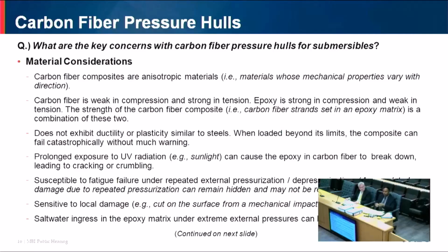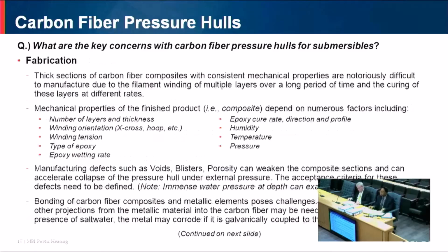Okay, now epoxy resins in general are highly resistant to saltwater damage. However, if you have voids in the epoxy, okay, we have air pockets, salt water can accumulate in these air pockets, and over time, this can form saltwater crystals. And then over several pressure cycles, this can cause delamination of the pressure hull under extreme pressures. Delamination means separation of the carbon fiber plies. Okay, so that is another damaging effect that is possible in carbon fiber composites. Next slide, please.